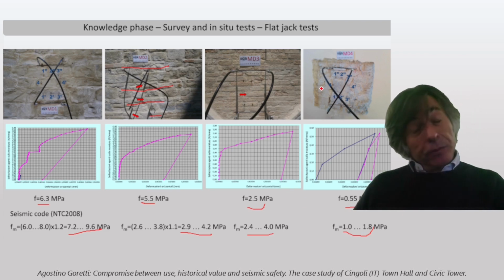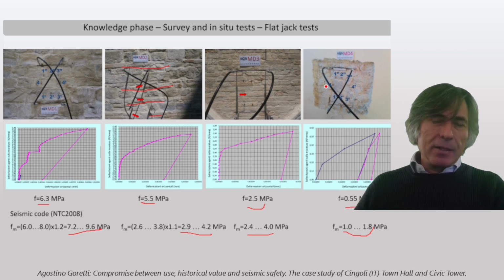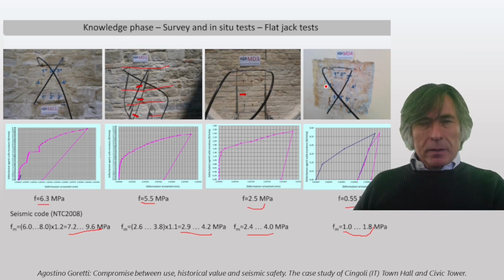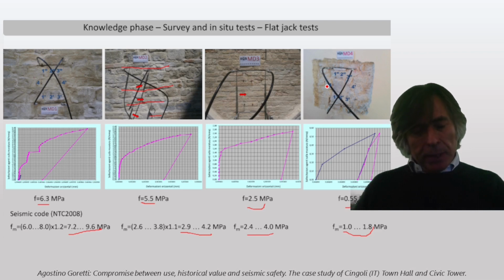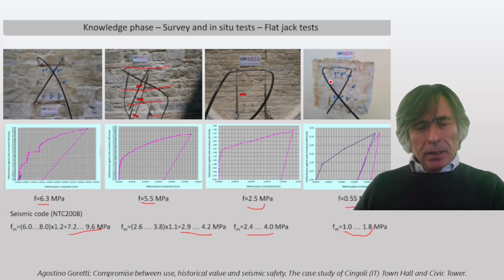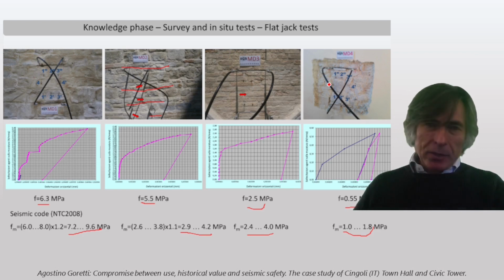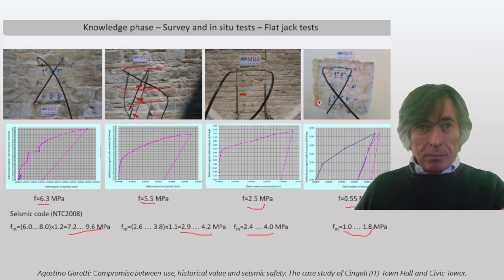But we know that for irregular masonry the results of the flat jack test are not so high, because the flat jack could rest partly on stone and partly on mortar, and according to what really happened at the support, at the interface of the flat jack and the masonry, there could be very different behavior. So the results are very uncertain, very scattered.